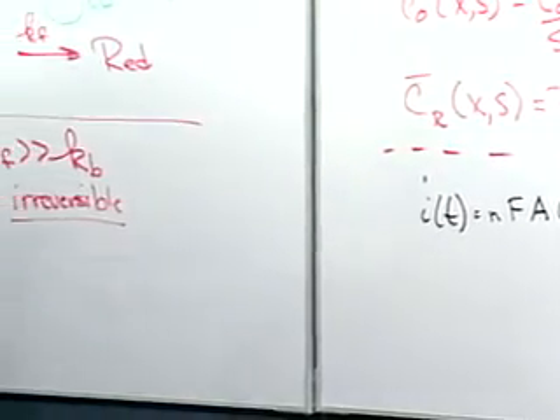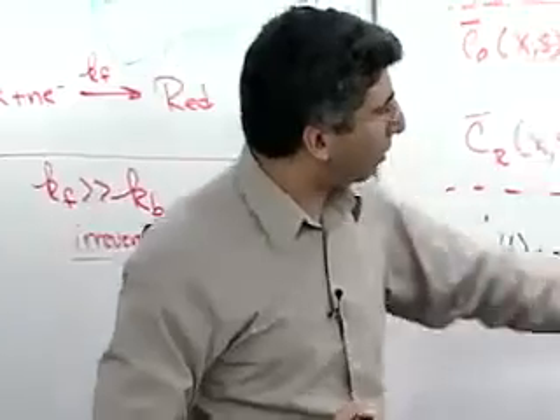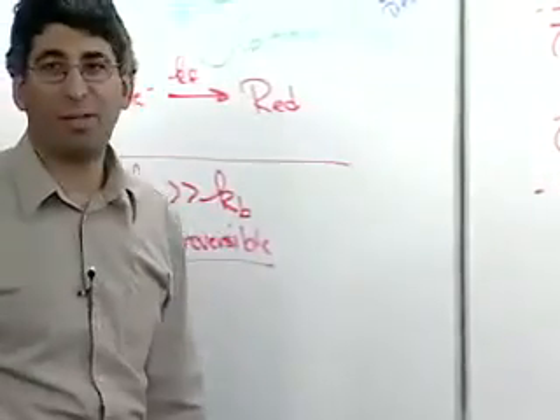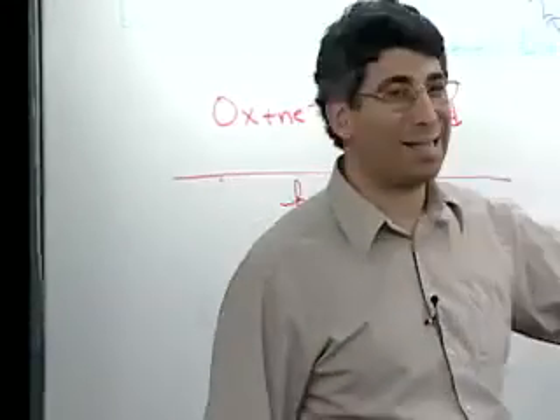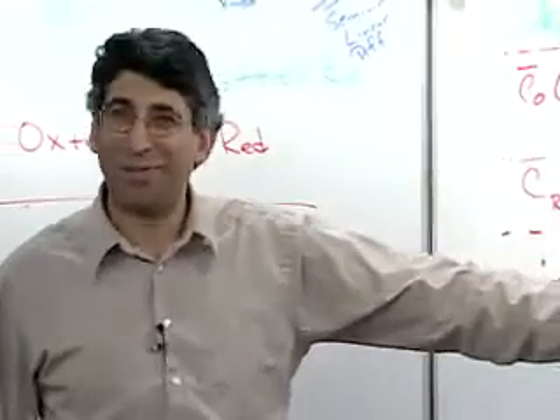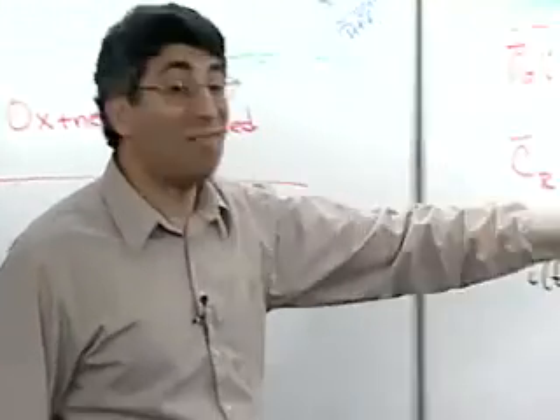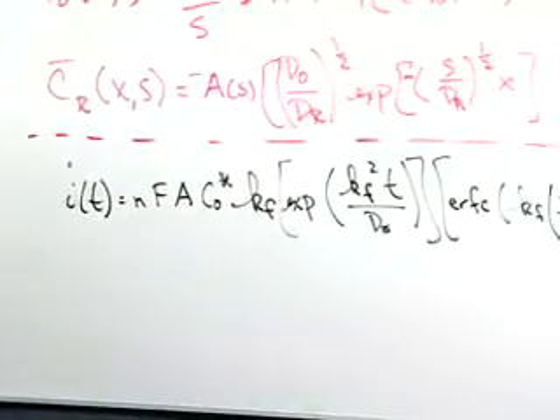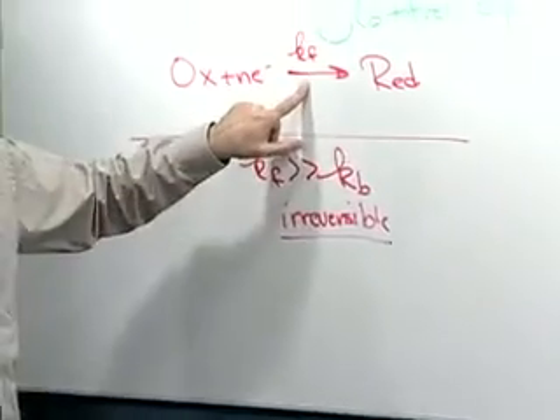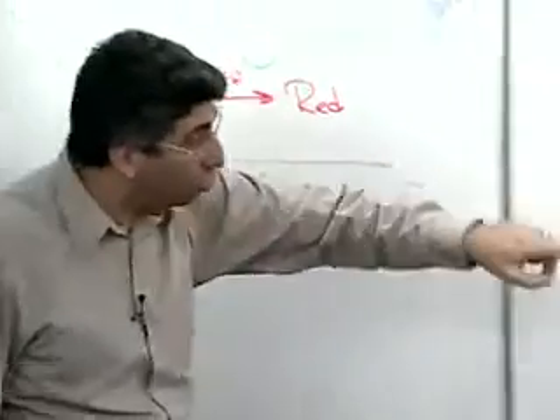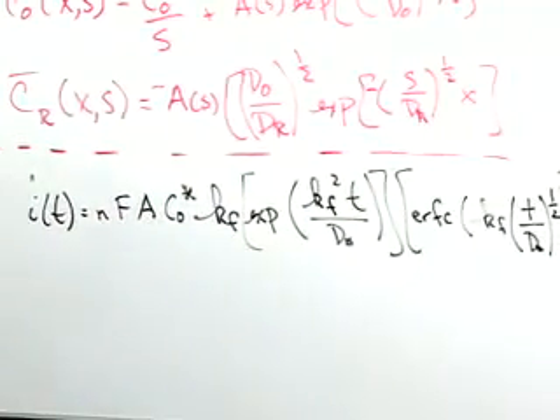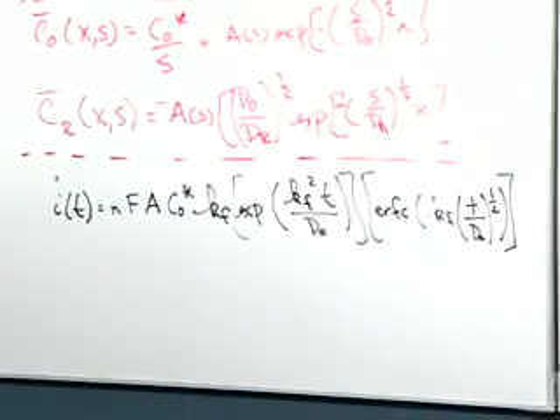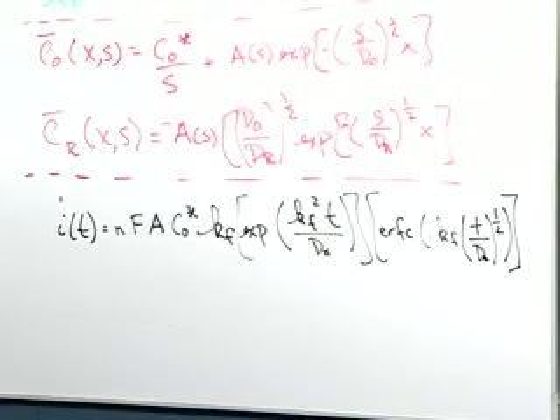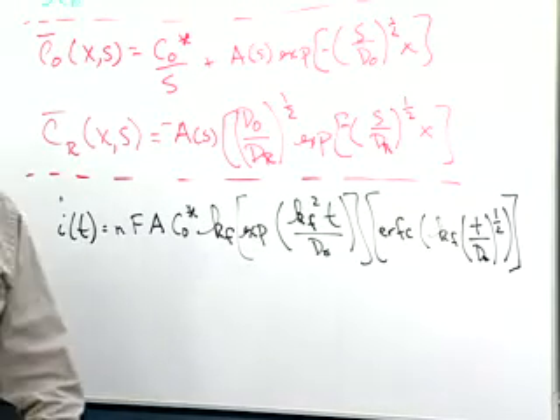Similar functional form, but you'll notice now that we explicitly only have to worry about the diffusion coefficient and the forward rate constant. And the key point to make here, the reason to show you this equation, because I doubt that this has any explicit meaning to any of you, is that even in the irreversible case, where charge transfer is limited by the forward rate constant, the diffusion coefficient still comes into play. There still is a diffusion component in this reaction. You can't say there's no diffusion. It's just charge transfer limited.